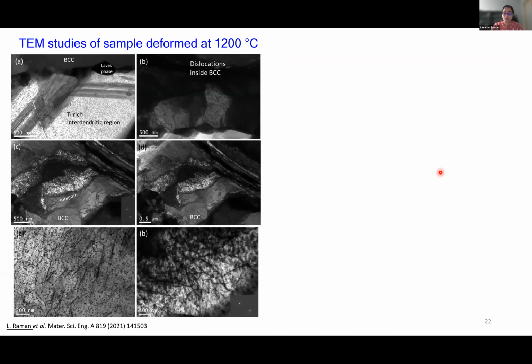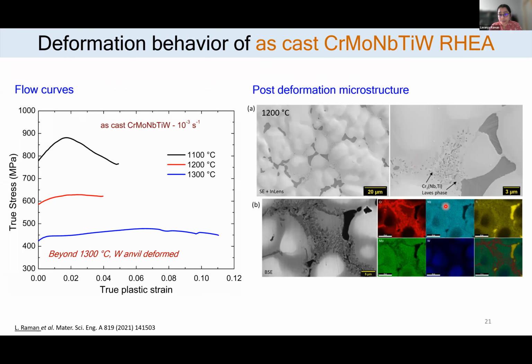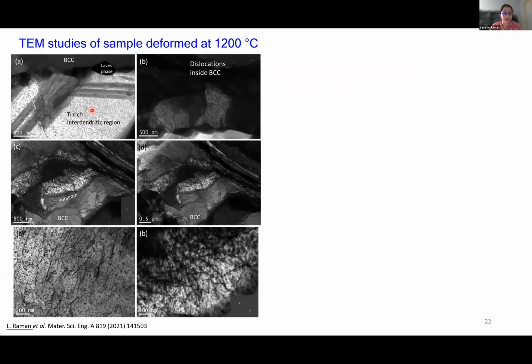So to understand the deformation mechanism, we took a TEM lamella from this region, where we have a BCC, this Laves phase, and some titanium-rich regions. As you can see, the titanium-rich regions showed some twin formation, and there were a lot of dislocations and subgrain formation in the BCC phase. The formation of subgrains is an indication of dynamic recovery happening. So in the cast alloys, we have dynamic recovery as one of the mechanisms. And we could also see a lot of dislocations in the BCC phase.